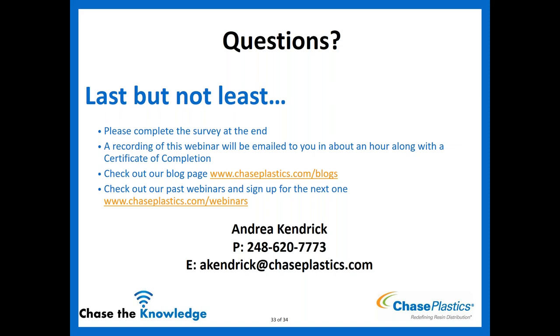Justin asks: how do indoor UV lights in stores affect products made from ABS, MABS, or SAN that sit on the shelf for extended periods? The answer is that it does affect them — not as severely as direct outdoor UV rays, but it will still cause yellowing and discoloration over time. Think of a thermostat housing in your house that starts to yellow after many years. Even filtered or indoor lighting will still affect these materials and cause yellowing, just more slowly than direct sunlight.